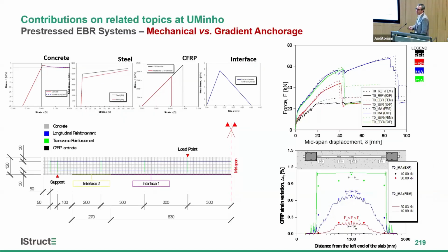Of course, we also did numerical modeling to try to understand if the existing models, or if the existing knowledge, is enough to simulate these pre-stressing systems. And you can see here basically the continuous lines are the experimental curves. The dashed lines are the numerical ones, and you can predict pretty well the response, meaning that using relatively basic constitutive models, nonlinear models, of course, we can catch very well the response, including in terms of strengths, and you can see here for different levels.